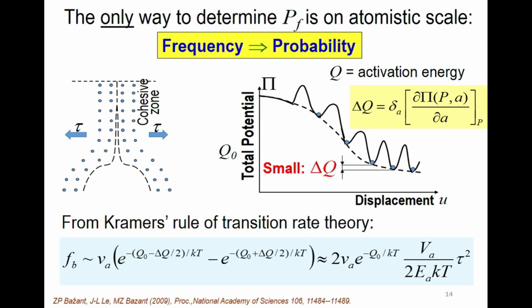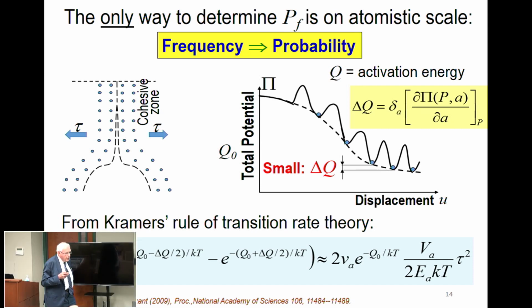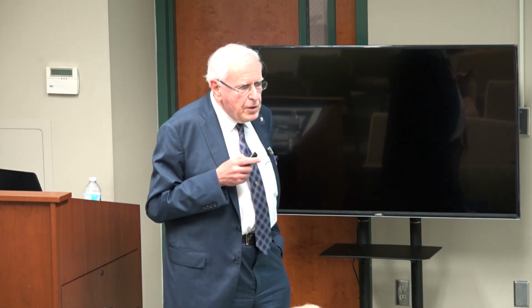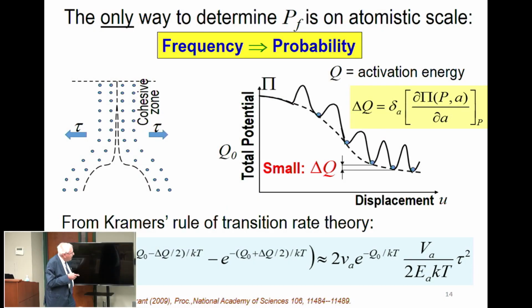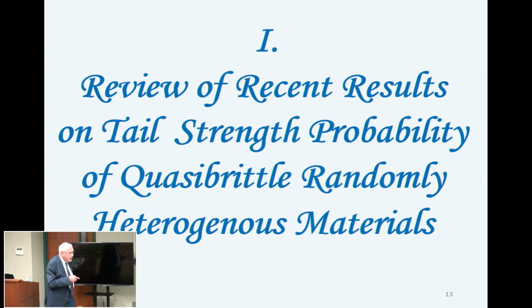So how to approach it? There is a theory of Freudenthal who derived the distribution by considering the statistics of critical size flaws, maximum flaws. But if you look at it, it's not a correct theory. It really relates one scale of flaws to another and derives one set of properties from another set of assumptions. The only scale at which the probability is known exactly is the atomistic scale. The reason is that at the atomistic scale, the frequency of the breakage of bonds is equal to the probability of the breakage of bonds exactly.